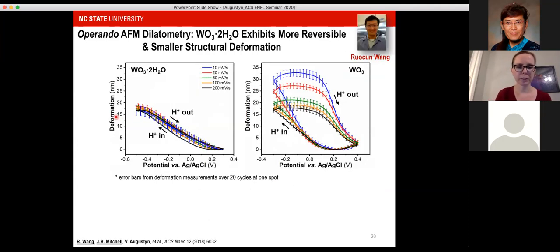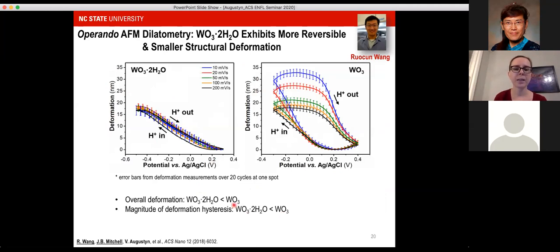This experiment was really interesting because it's actually how we got to this first clue that the structural change was a big difference between the two materials. For the hydrated material, we saw that its deformation for the same thickness was always less than the anhydrous material, and that there was essentially no hysteresis in this deformation for the hydrous material as there was for the anhydrous one. And anytime you see a hysteresis for any type of material's property, it is indicative of the fact that the forward and the reverse paths are not the same. But that was not the case in the hydrous material. So same redox, tungsten 5+, 6+, but very different mechanical response.